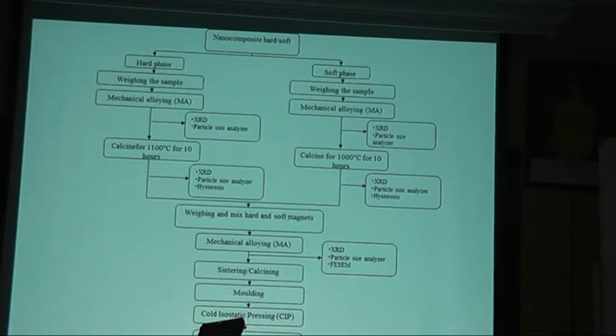For the hard phase, we have two candidates. We can use strontium or barium ferrites. And for the soft phase, we can play around. For the time being, I think nickel zinc is the best candidate, or maybe we can use another soft phase. Maybe the question is for nickel zinc, whether 0.7, 0.3 or 0.8, 0.2. I don't know which one is the best.